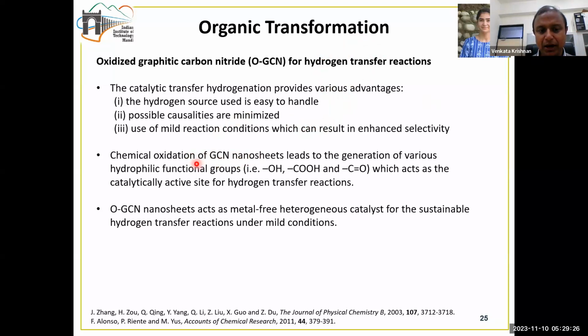So typically the chemical oxidation leads to hydrophilic functional groups being incorporated on the surface of the graphitic carbon nitride nanosheets. This includes the OH functional group, the COOH functional group, and also the carbonyl functional groups. And these act as the catalytic active sites for the hydrogen transfer reactions. This material, we call it the oxidized form of graphitic carbon nitride, OGCN. These nanosheets act as a metal-free heterogeneous catalyst for sustainable hydrogen transfer reactions under mild conditions.